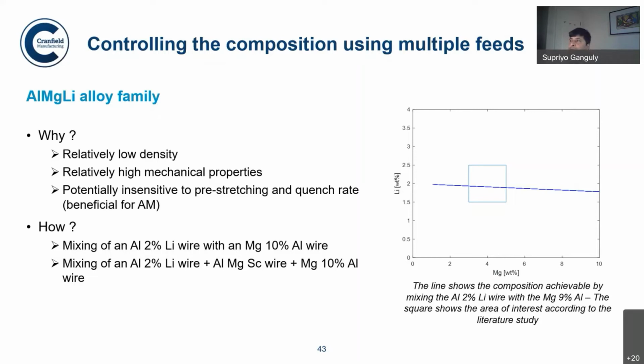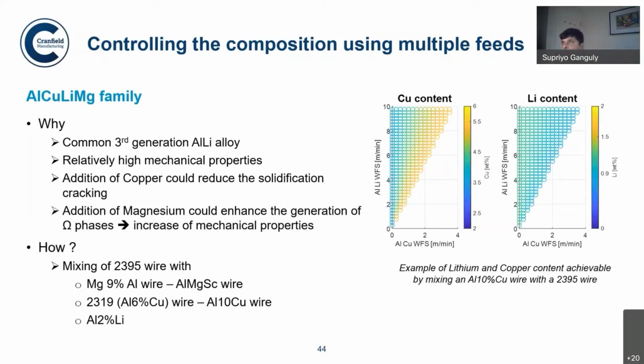And if we know the weight percent composition of each wire, then we can generate a target composition by controlling the feed rate of the different wires. So this is exemplified in this particular work. Just to let you know, these works are done to research how the composition can be adjusted to get an optimized composition for a particular type of application. And then we work with different wire manufacturers, so that this type of wire can be manufactured to the specific chemistry. In practical applications, you then don't have to mix, and can use a relatively straightforward process in order to generate a deposit.